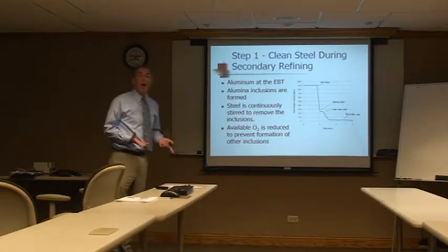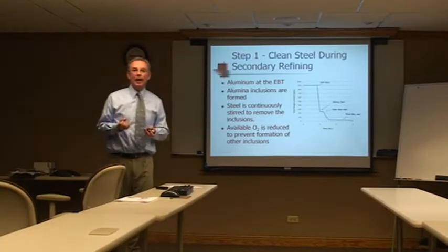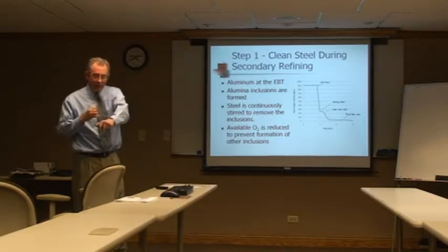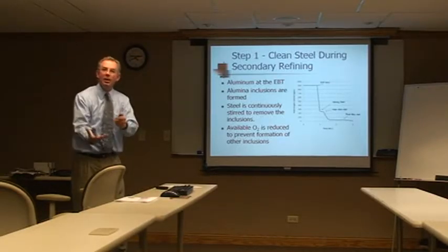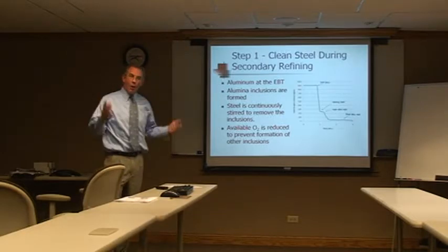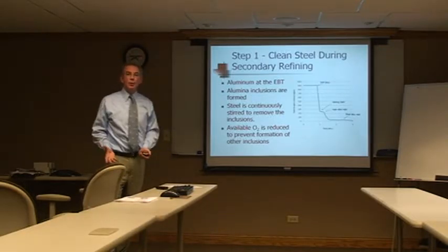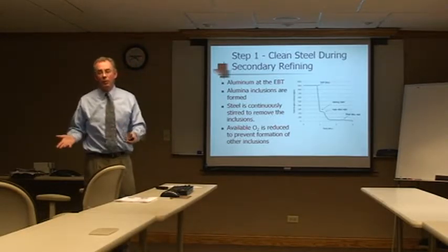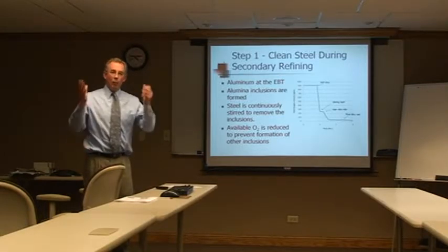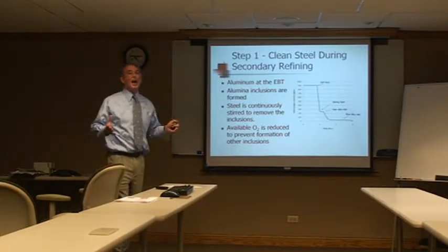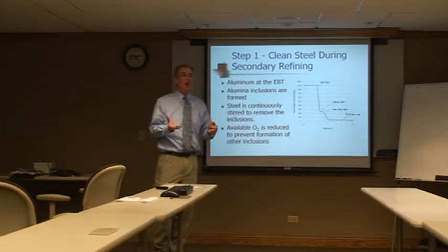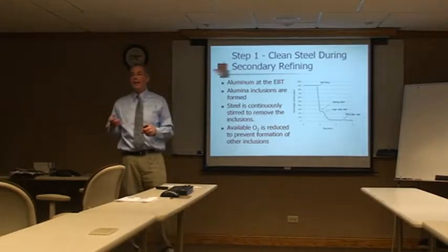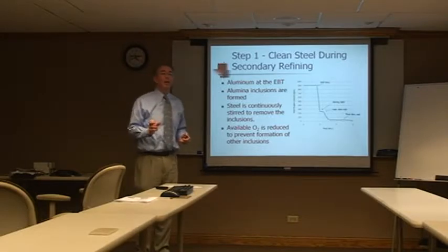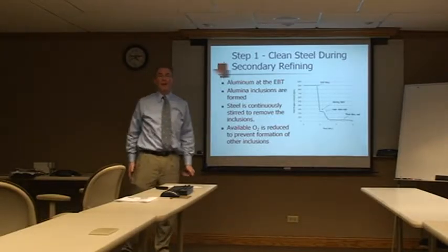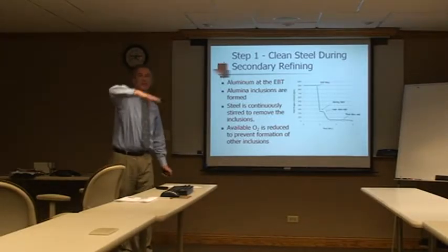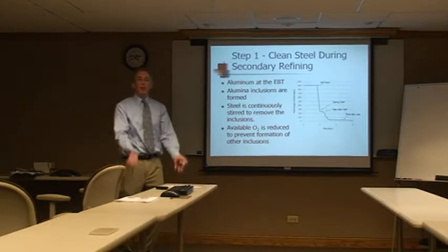Why do we want to create aluminum oxide? Because it's light. Okay? It's a liquid. When the heat is tapped into that ladle, onto the aluminum, on the bottom of all of that, oxygen is reacting with the aluminum, assuming we have enough aluminum, which we do. And now we still have a ladle of 1,000 ppm oxygen, but now that oxygen is in the form of aluminum oxide, Al2O3. It's a liquid inclusion, which theoretically, if we sat there and we let that ladle sit with our top slag, Stokes' law, those are going to float.